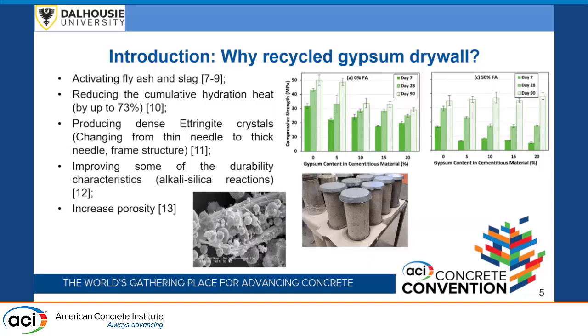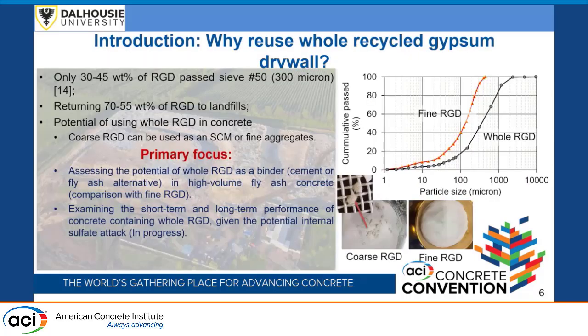It can produce dense ettringite crystals, so it typically changes the thin needle to thick needle ettringite and provides a frame structure which can carry load. It can also improve some of the durability characteristics, including the resistance to alkali-silica reactions. However, it increased the porosity of the system because of the fines that we have, and we will explain it in the next slide.